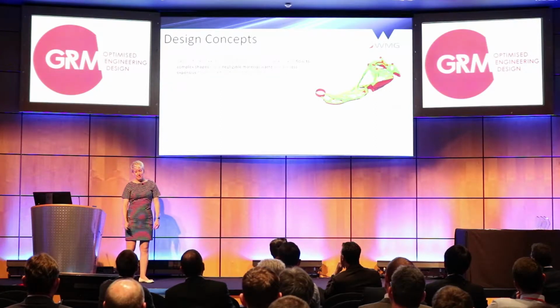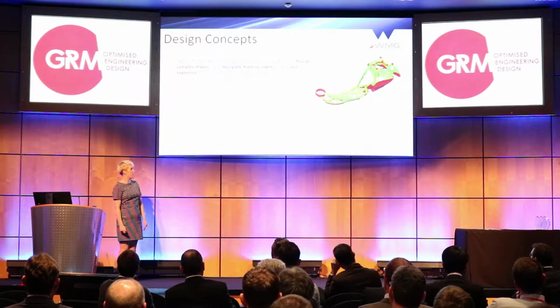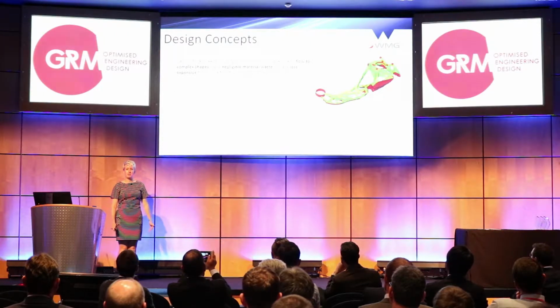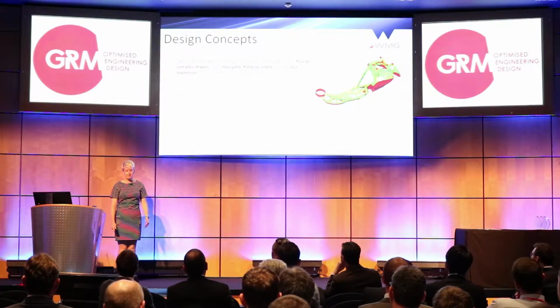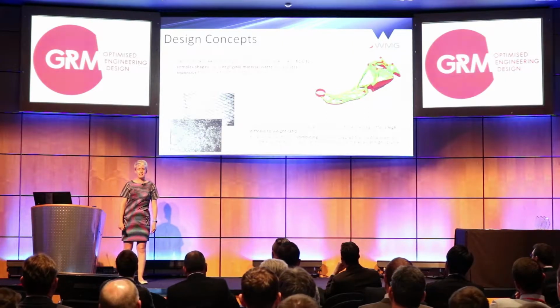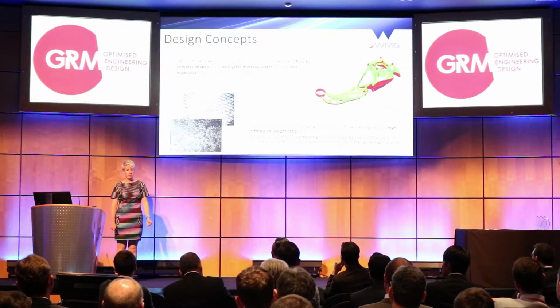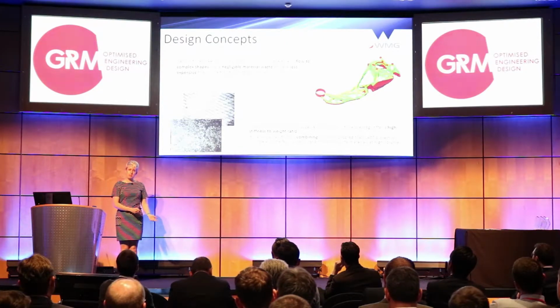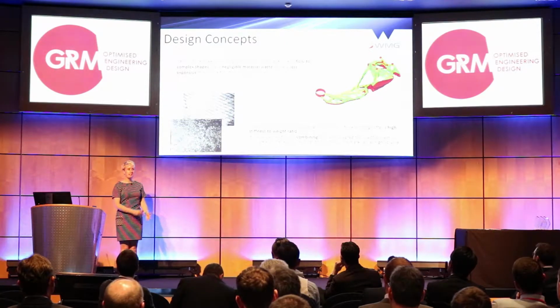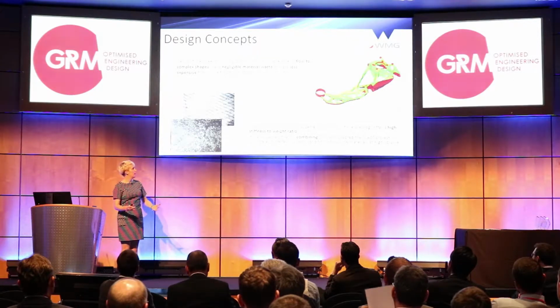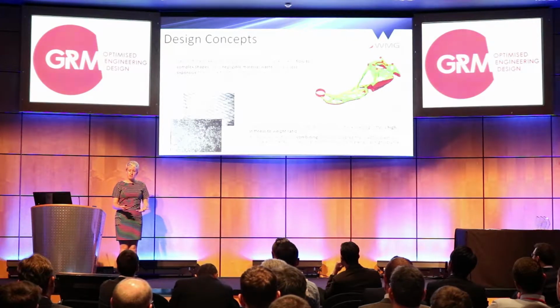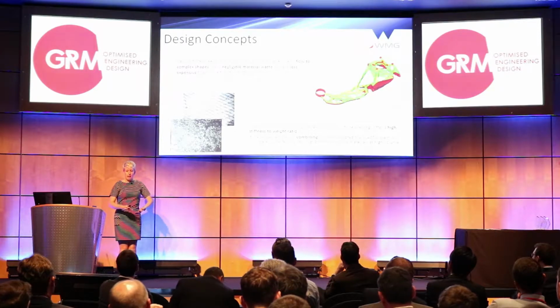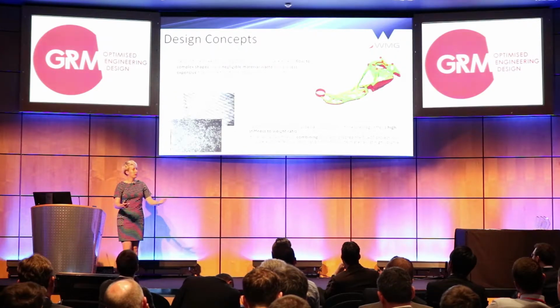However, we couldn't make it all from SMC because the stiffness requirements were too high. I think the first designs were coming out with thicknesses of around 30 millimetres, so this wasn't feasible. So the next step was we wanted to combine it with pre-preg. So pre-preg is your more traditional carbon fibre composites with continuous fibres which will take the load and meet the high stiffness to weight requirements. And we thought we can combine these two and come up with the answer.